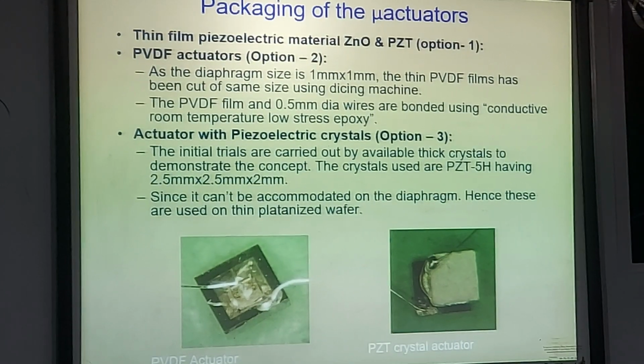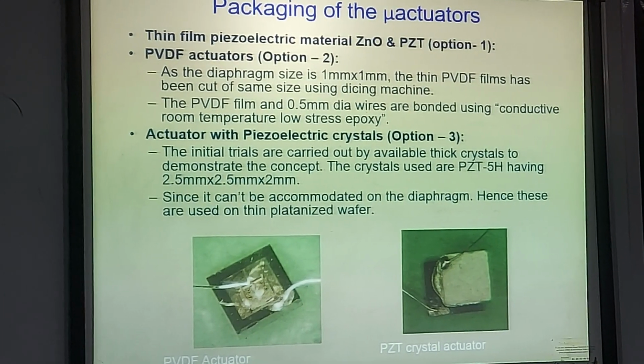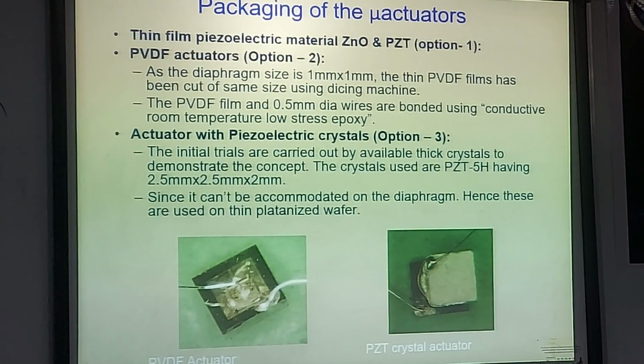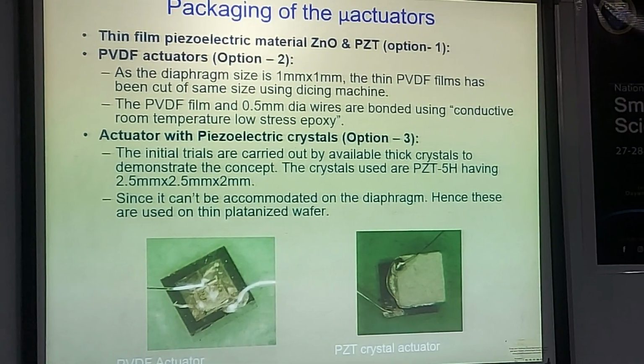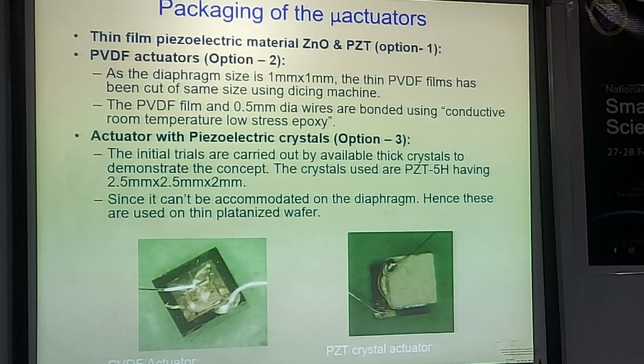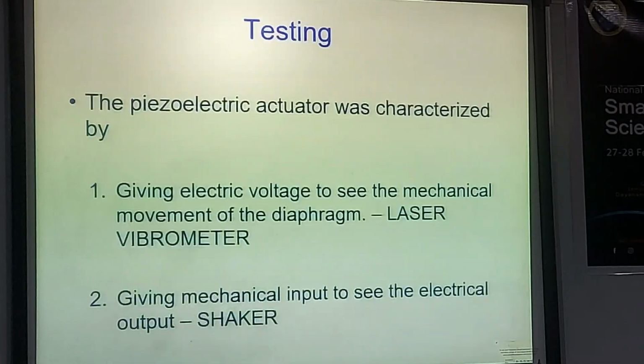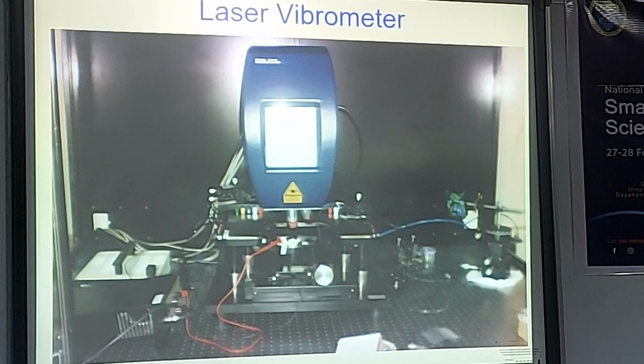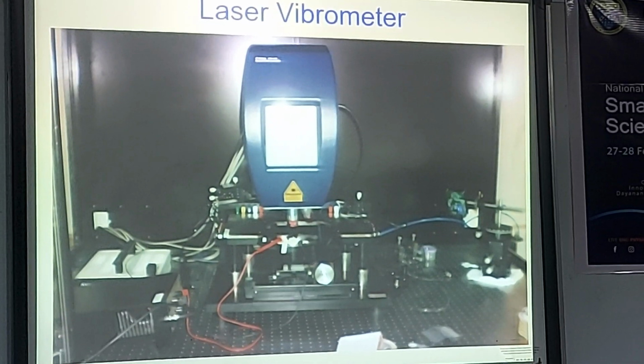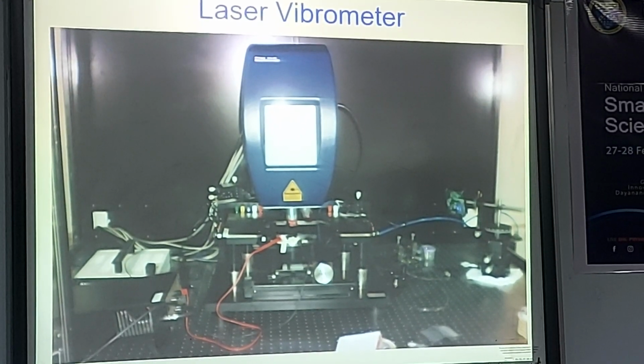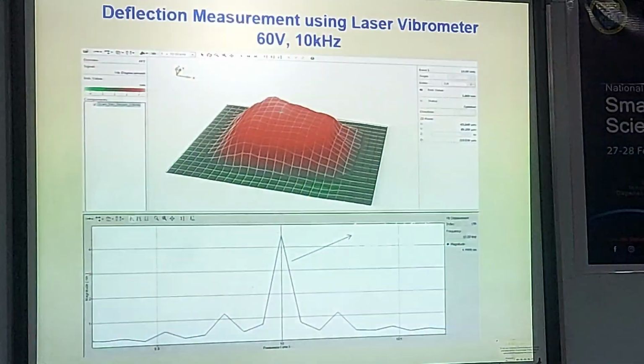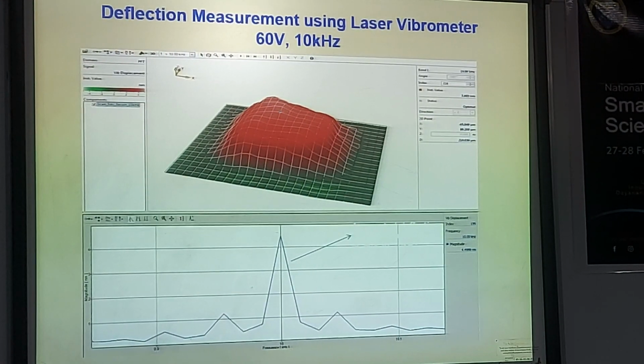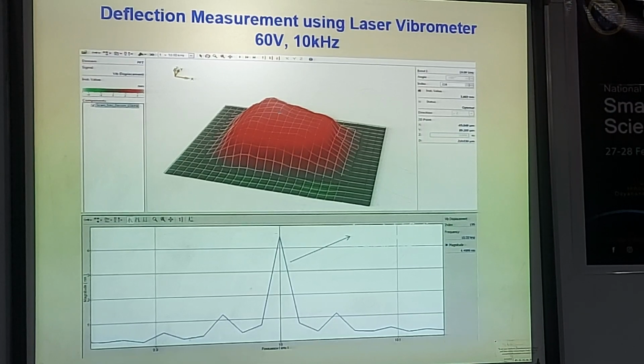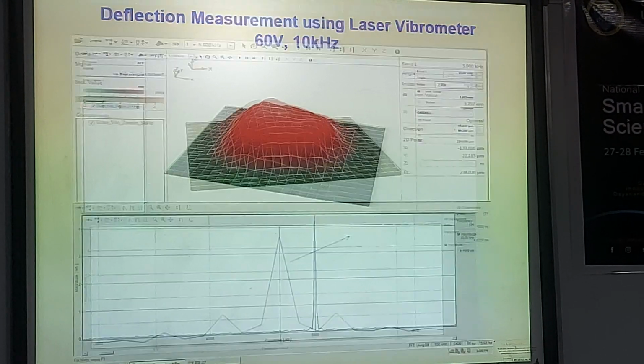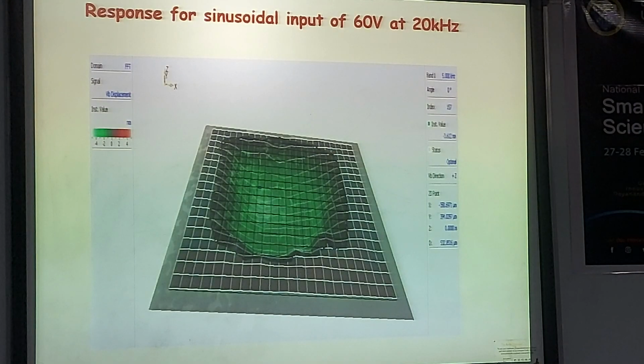These are some of the analyses that we did. This is the silicon diaphragm onto which we initially used a piezoelectric crystal and tested the property of this actuation, and later we replaced it with a thin film. The performance was studied using a laser vibrometer arrangement which is available in our institute. These are some of the data: deflection measurement using the laser vibrometer with a potential of 60 volts and 10 kilohertz. And some more data. And there is an animation, I don't know whether it works.